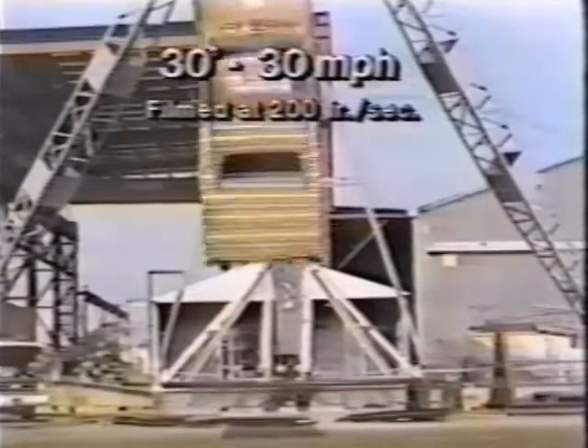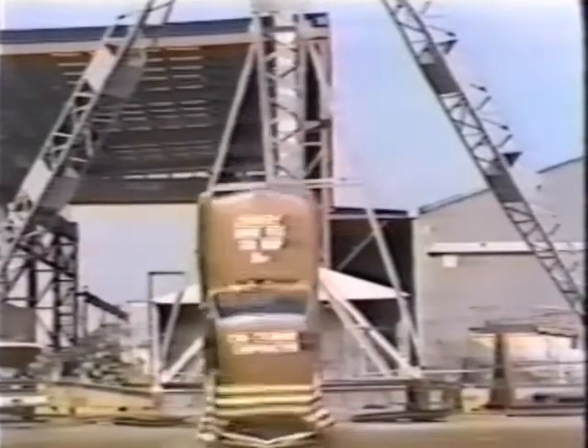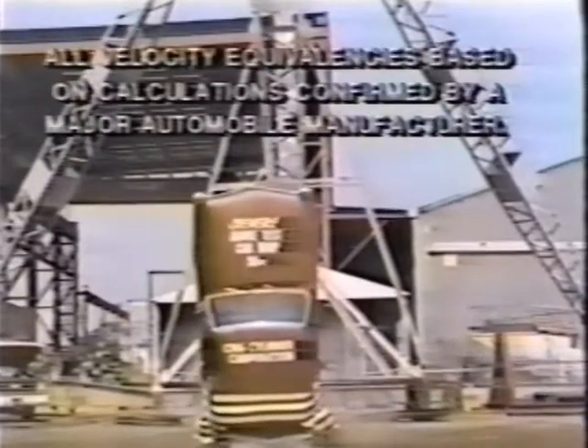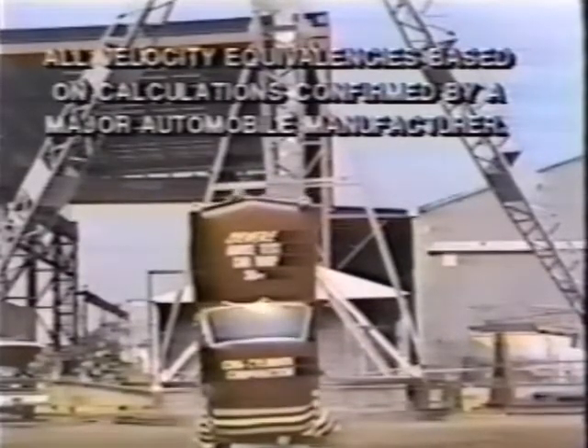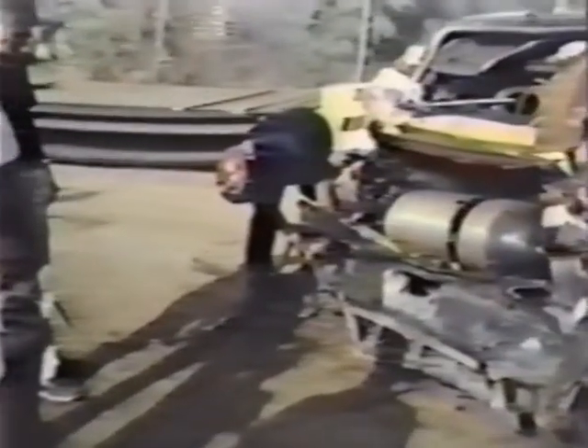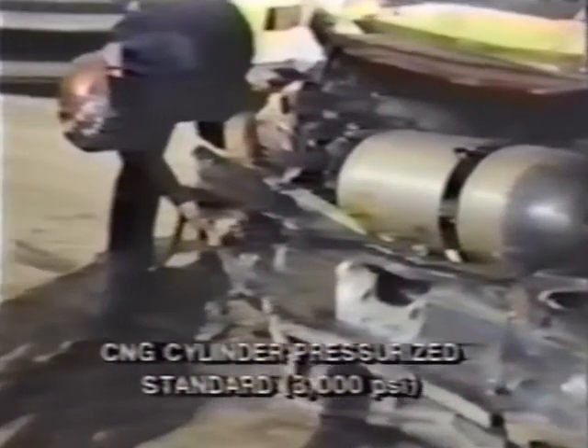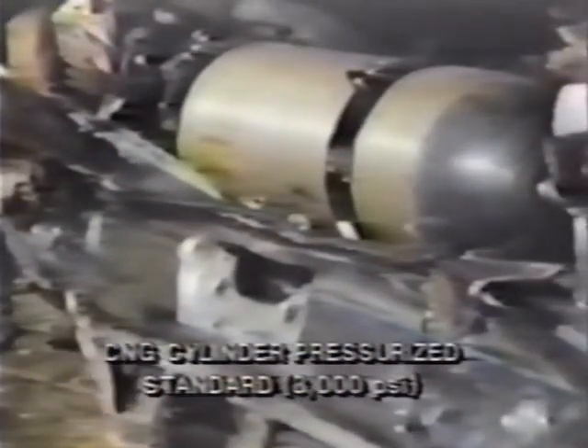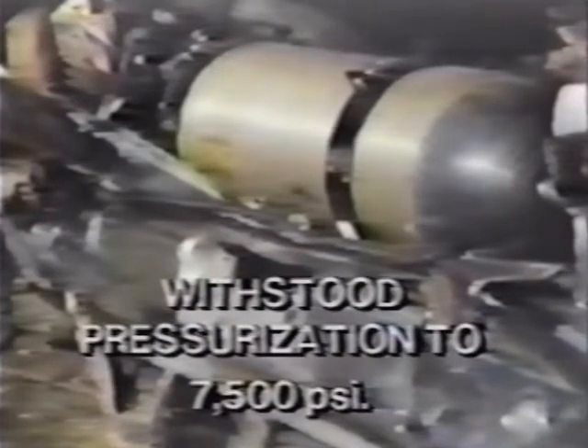Dropped from 30 feet, this 1966 Pontiac was moving at approximately 30 miles per hour at the point of impact. That is the maximum speed at which new car makers are required to test the integrity of conventional gasoline tanks. The CNG cylinder, pressurized to a standard 3,000 PSI and mounted in the trunk of the car, withstood the rear-end crash with no meaningful damage or dislocation. Fuel lines to the engine were kinked, but showed no damage. Subsequently, the same cylinder withstood pressurization to 7,500 PSI, the minimum burst pressure required by federal and Canadian government authorities, showing that the tank had maintained its integral strength despite the crash.